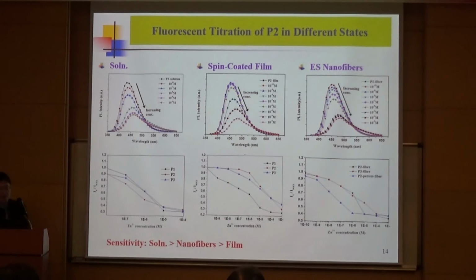So we just choose one type of metal ion, zinc ion, to study the sensing performance of the P2 random copolymer in three different states: dilute solution, spin-coated thin film, and electrospun nanofibers. The fluorescent titration shows similar fluorescent response. With increasing ion concentration, we observe fluorescent quenching with redshift in emission peak. However, the sensitivity toward ion concentration was different among the three states. We observed the best sensitivity for dilute solution, slightly poorer sensitivity for nanofibers, and the worst sensitivity for the thin films.